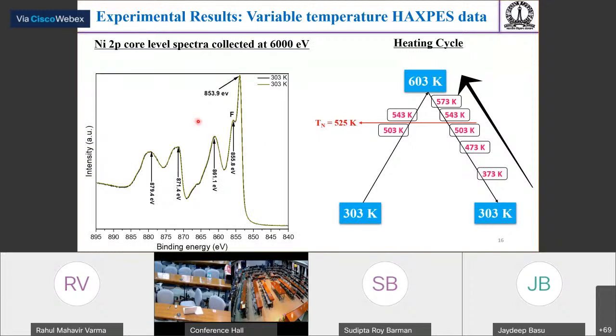So this is the nickel 2p core level spectra collected at 6000 electron volt energy. These two spectra are at room temperature. One is before starting the heating and one is after the heating, and we can see both of the spectra are overlapping on top of each other, which negates the possibility that the sample is getting bad at the high temperature. Similarly, we have collected twice at the highest temperature, that is 603, and again we can see a good match of nickel 2p core level spectra.